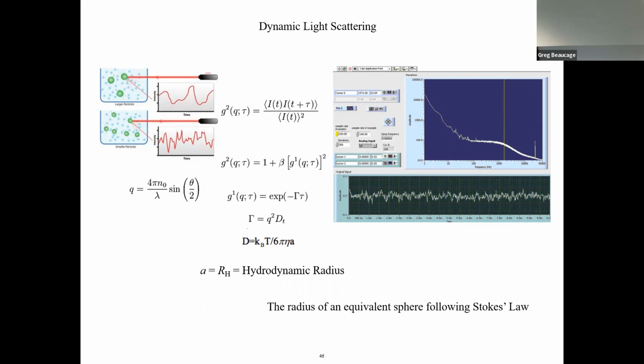So you try to dilute down the sample. And in the DLS, what they do is do backscatter, because the beam can only pass so far through, and they assume that you only get a sample that isn't multiple scattering when you take backscattering from it. So it's possible to do DLS on milk in a backscatter mode.